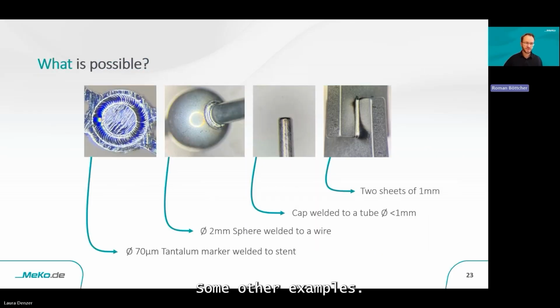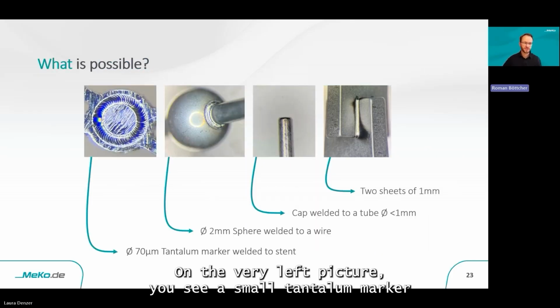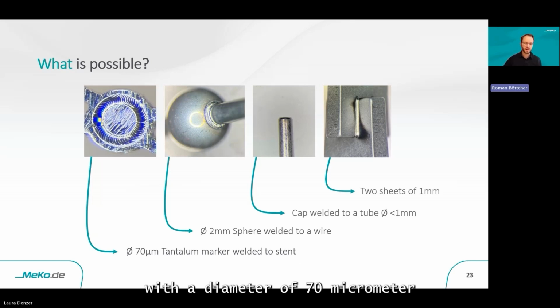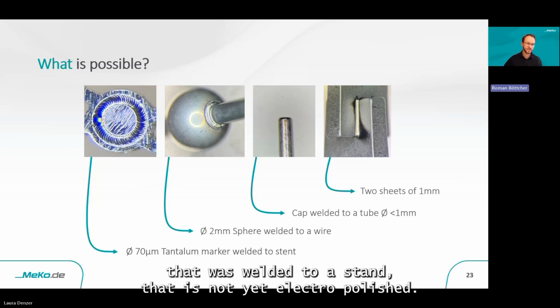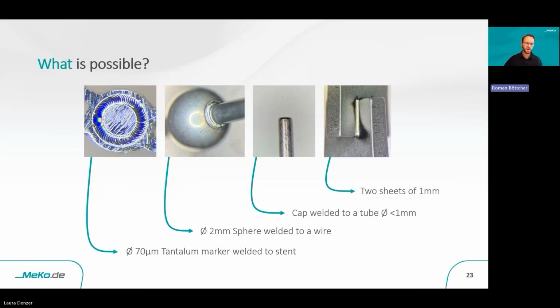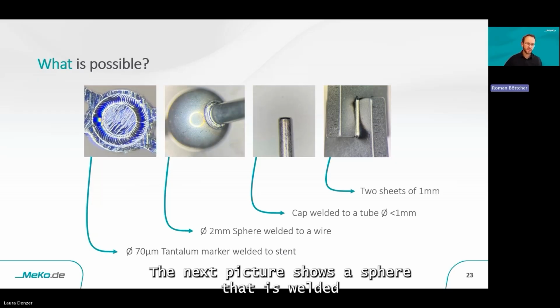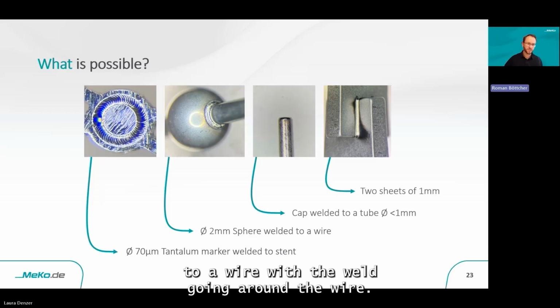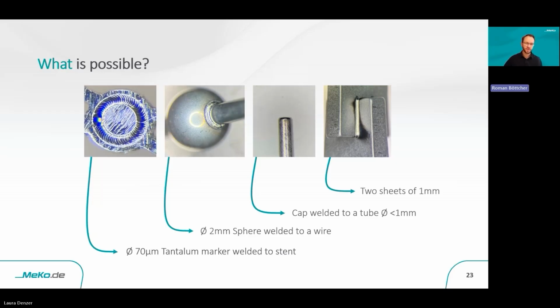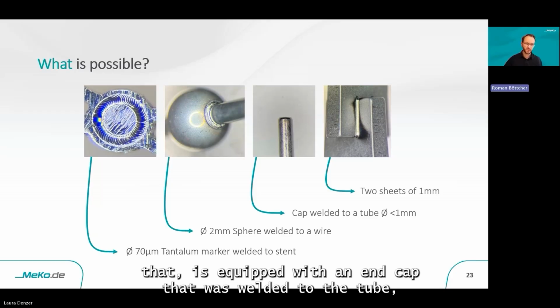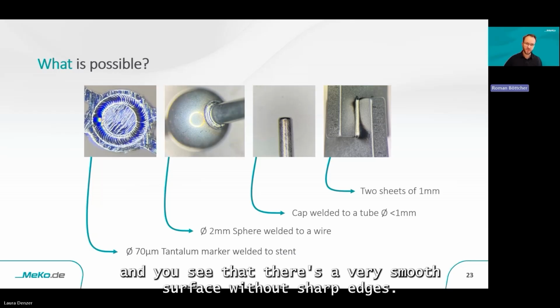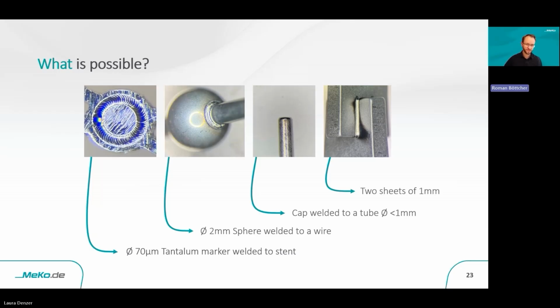Okay, some other examples. On the very left picture, you see a small tantalum marker with a diameter of 70 micrometer that was welded to a stent that is not yet electropolished. The next picture shows a sphere that is welded to a wire with the weld going around the wire. The third picture shows a small tube that is equipped with an end cap that was welded to the tube, and you see that there's a very smooth surface without sharp edges.